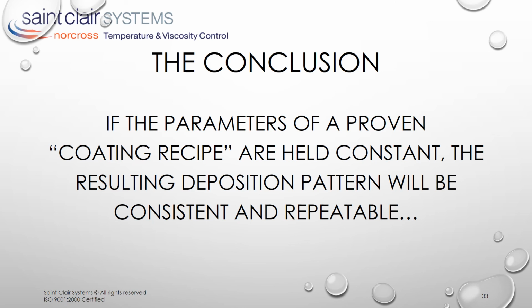In each case, temperature variations result in viscosity variations that undermine those advantages. In fact, these newer, more modern coating formulations are often even more temperature sensitive than their older counterparts. Modern temperature control systems utilize innovative methods and devices to assure that temperature-based viscosity variations at the point of application are eliminated and that consistent, repeatable performance can be achieved independent of changes in ambient temperature and/or processing conditions. This converts temperature into a tool that can be used in conjunction with other tools like pressure regulation, speed control, and the like to assure that the outcomes of the coating process are predictable and repeatable and advance the goals and objectives of your business.